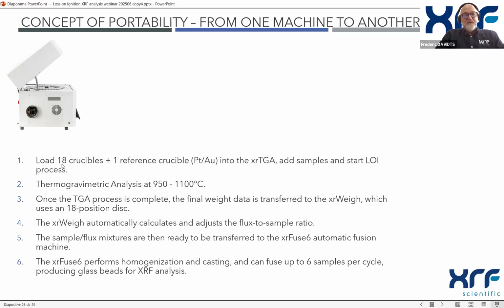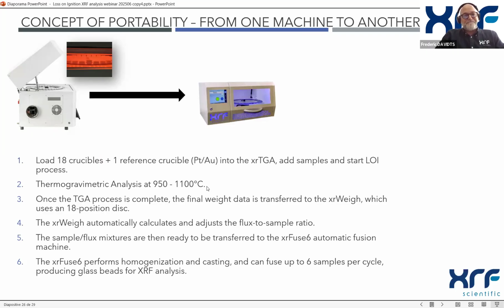In this case, we will use 18 crucibles and one reference crucible. The crucibles used are made entirely of platinum-gold. So we'll start the process, doing the thermogravimetric analysis at 950 or another temperature up to 1100 degrees. Like I told you, it could be interesting to measure the loss of mass at the fusion temperature.